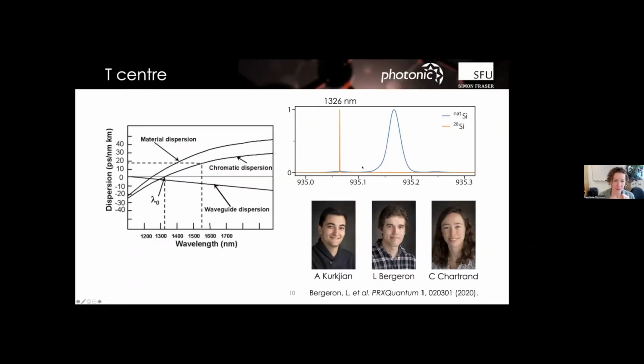So you might ask why we picked the T center. This is 1326 nanometers. Let me see if that'll play now. There we go. So you might ask why we would take a look at the T center when I said that there's a family of other opportunities. One of the reasons is that this is right in the O band, and the O band is around 1310. That is the single mode fiber infrastructure in all modern data centers. So that's good. Single mode fiber is around the O band, which is phenomenal. And it's also the zero dispersion point for said fiber. So from a long distance perspective, there are a couple of different things. It's also easy to make, but this is the one that we're pushing on the most quickly right now.